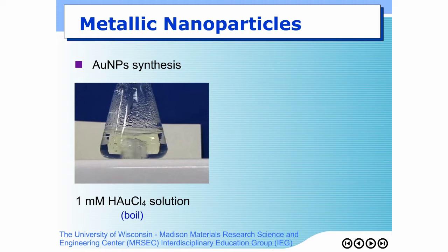As we explained earlier, we want the reaction to be really fast, right? So that the nucleation takes place at the same time, and all nuclei are formed at the same time. The higher the temperature, the higher the rate of reaction. And the higher the rate of reaction means we produce all the growth species at the same time. Okay?